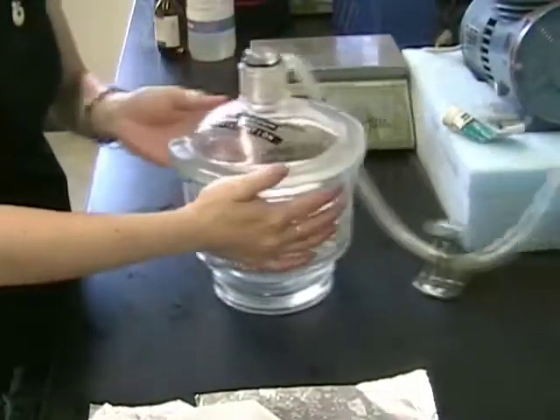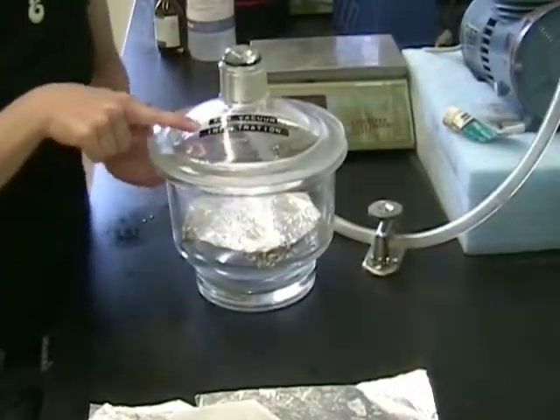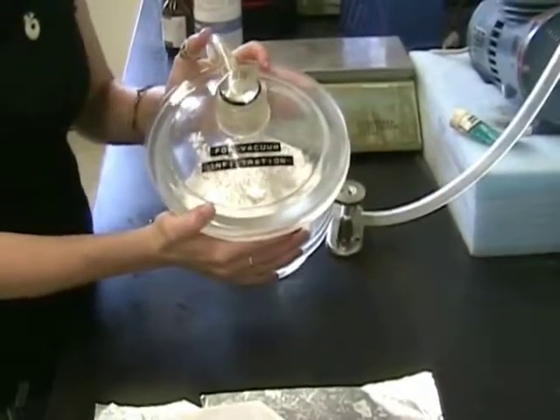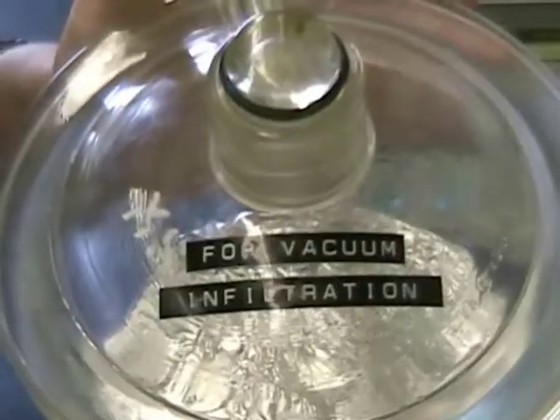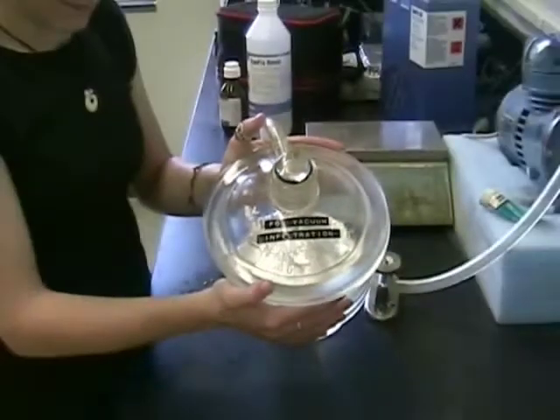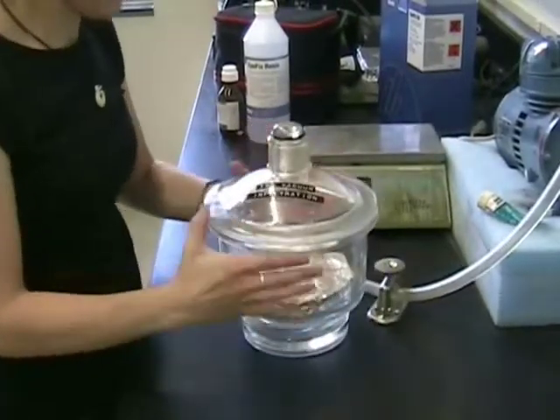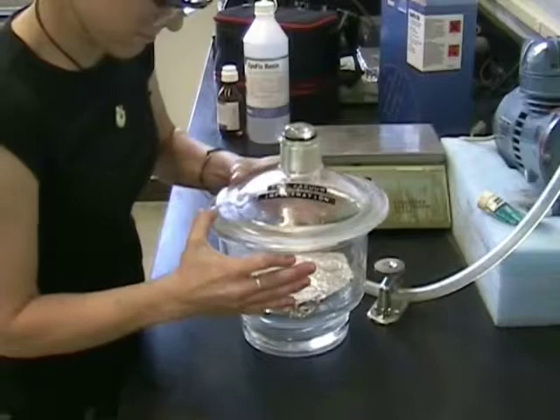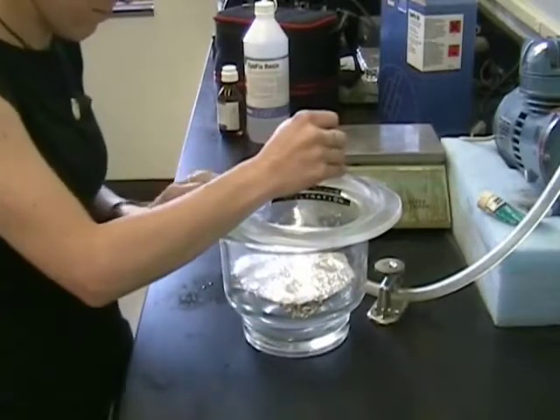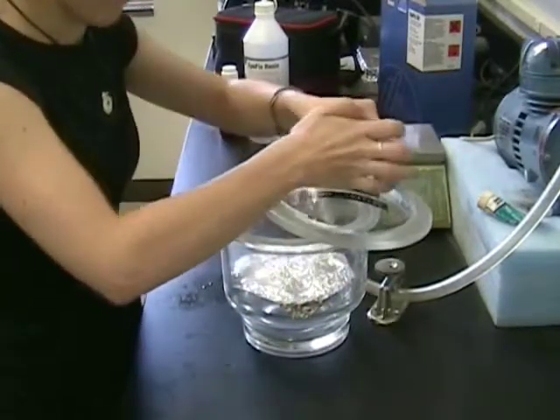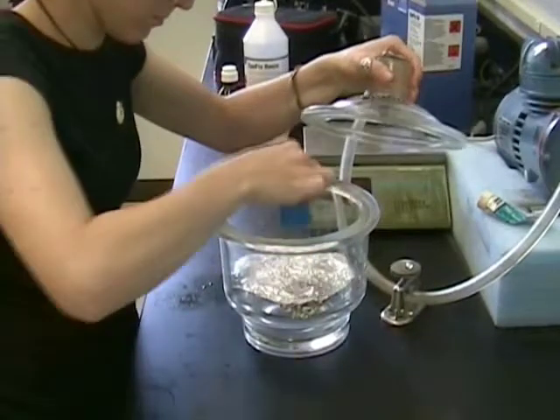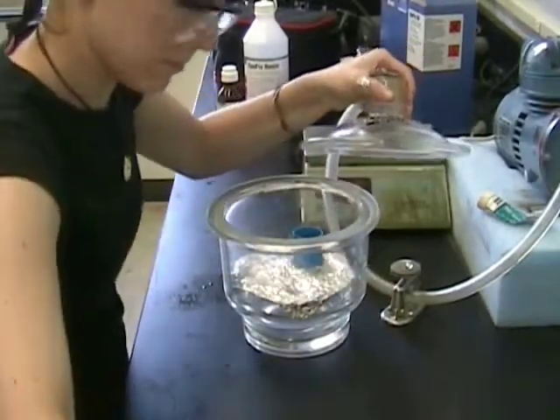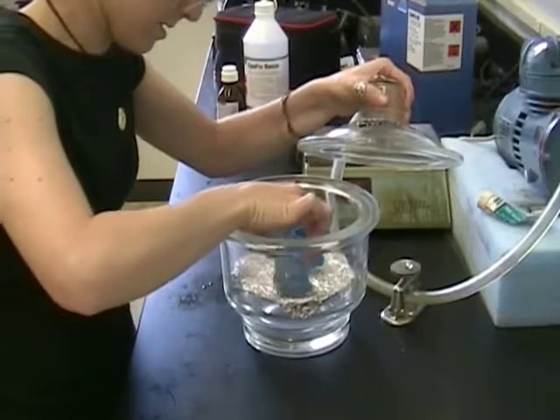Vacuum infiltration is done to remove air bubbles and fill any pores. It's only done with cold mounting. Vacuum infiltration is done for porous samples to get rid of any air bubbles from pouring the epoxy and to even out the epoxy in the small containers. The lid of the vacuum chamber is particularly hard to get off, as you can see. You place the samples into the compartment, put the lid on,